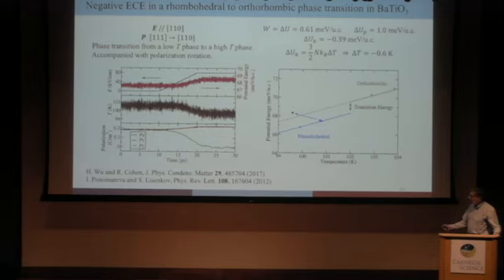The biggest consequence is losing this Z component of polarization. The X and Y go up a little bit along the electric field direction. You can think of it this way. As a function of temperature, the rhombohedral potential energy is lower than the orthorhombic, but as you apply electric field, you're driving the system to higher potential energy and lower temperature, and it's crossing over to the orthorhombic state. And so you see a change in temperature of about -1 Kelvin as a result.